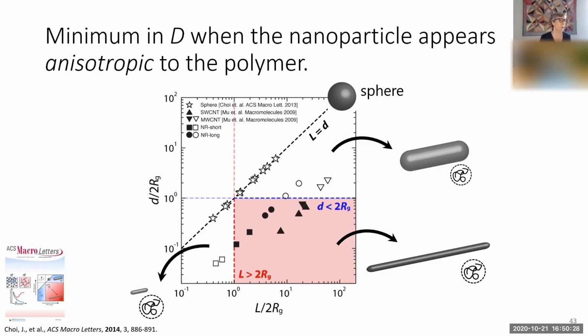Now, Jihoon and Russ also have a paper about particle diffusion, nanoparticle diffusion, rod diffusion, and there is a difference. They move along their axis faster than they do laterally because it's kind of like reptation, right? You're running into entanglements if the rod moves left or right, but if the rod goes straight ahead, it's faster. Okay, cool. That's interesting.